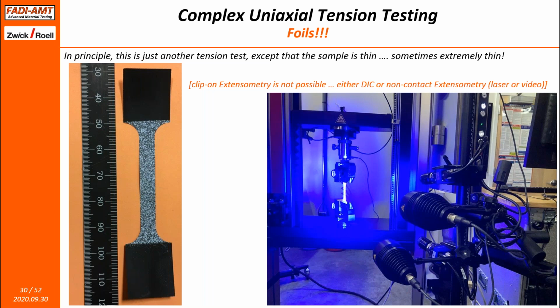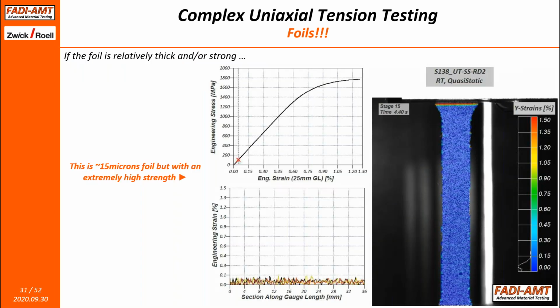Now, once we enter the foil domain, when you drop below 500 microns, like half a millimeter, it's really difficult to use any clip-on extensometer because you're going to damage the sample before you start the test. So that's ruled out. You have two options: either use DIC or any other non-contact extensometer technology like laser or video. That sounds okay, and in many cases, yes, video or laser extensometers can work.